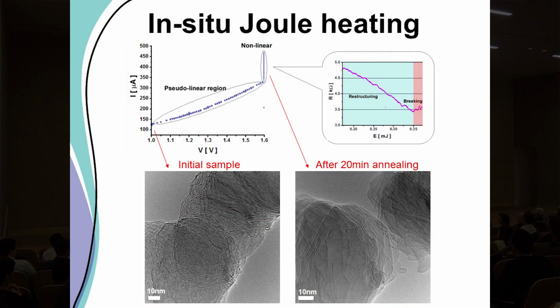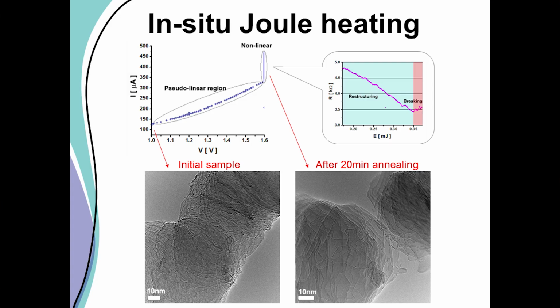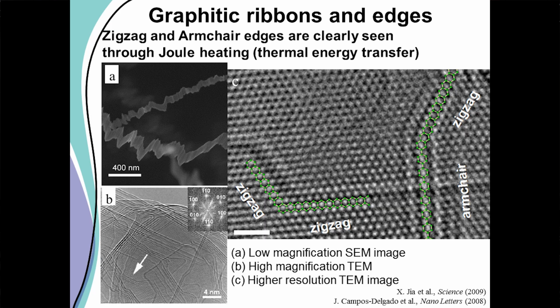And when you get into this regime, you start annealing the sample. The sample goes up to about 2,000 degrees centigrade, and we get something that looks like this. So this is the original material, and I showed you we have electrodes across a piece of this. And this is when it shoots up, the current IV characteristics. So this is seen in an ordinary TEM, not a fancy one. This is done in a student instrument that's used for the lab course. So it's not very fancy. But the result is interesting.